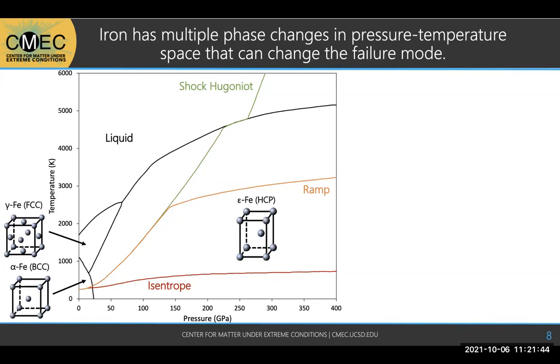So another important part of iron is that it has multiple phase changes, in pressure, temperature space, and those phase changes can change the failure mode. So it's really interesting, kind of an interdependence. At ambient conditions, you have this BCC structure. You can see that in the little unit cell in the bottom left there. And then at higher temperatures, you have this FCC structure. But what's important for these shock experiments is the high pressure phase, which is the HCP. And so this transition occurs at pretty low pressure, maybe around 13 GPa or so. It can vary between static diamond anvil cell experiments and laser shock, but it's around there. And so most of these high pressure experiments that I'm looking at look at this HCP phase.